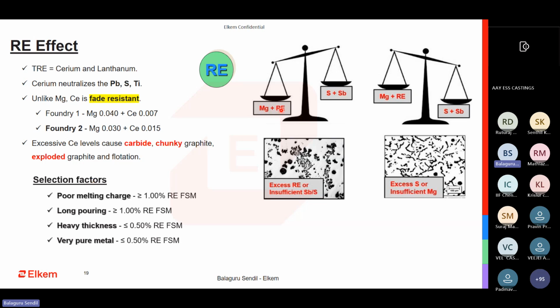When you have more magnesium and rare earth and the sulfur level is 0.015, but in this case, if I take Foundry 1, the magnesium is 0.040 and the cerium is 0.007. So here, if the sulfur is low, then I might end up getting this sort of chunky microstructure. Here with 0.030, if the sulfur is balanced, then I would get a very good microstructure. So the problem is that when I have more magnesium and more rare earth and very little sulfur, I will end up getting chunky. If I have more sulfur and very little magnesium and rare earth, then I will end up getting CGI. As I discussed earlier, sulfur is also very important. If the sulfur is too low, 0.006, 0.007, then it is not an ideal situation. You will end up with problems of chunky. If the sulfur is too high, 0.020, 0.018, then you might end up getting CGI.